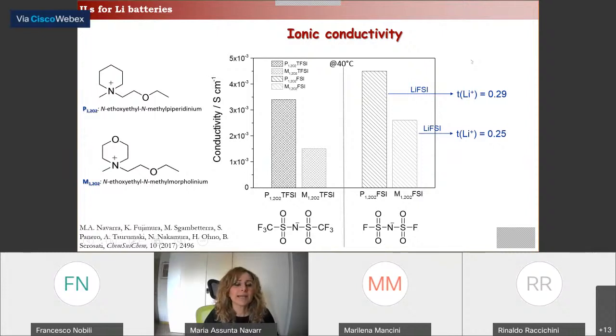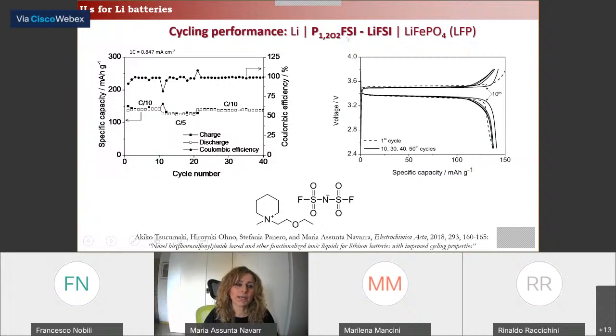That's why this time we could use this particular ionic liquid as pure main component of the electrolyte together with a suitable lithium salt. And its performance was tested in a lithium cell coupling a lithium iron phosphate cathode. Here the specific capacity and the voltage profile are shown.